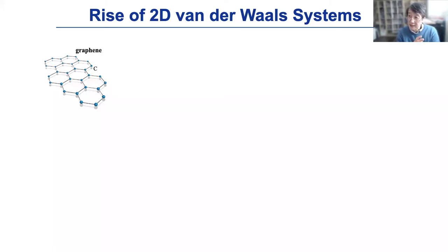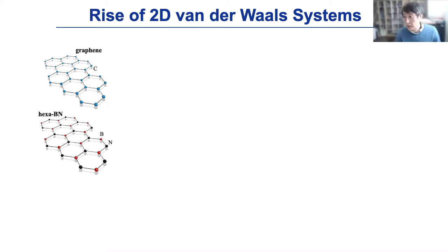But in some sense, graphene also served as a good starting point. The community started to look for materials very similar, but also of a different kind. Boron nitride is a good example. It is an insulator with a graphene-like structure, and within the layer, all the chemical bonds are there, but in between the layers, there is a weak bonding force. So like graphene, you can extract one single layer, but unlike graphene, because of the different atomic structure, it is a good insulator or good dielectric.